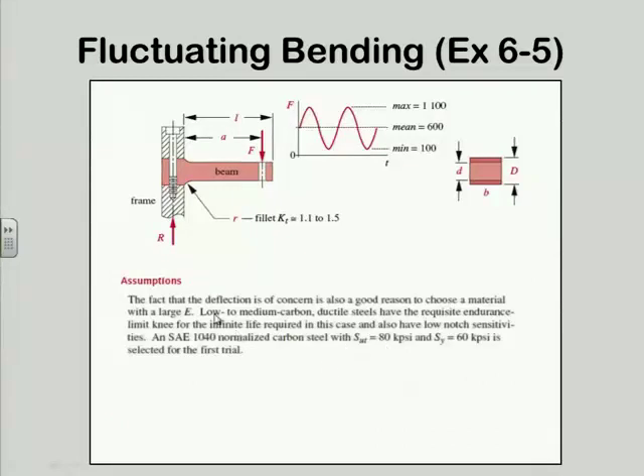I'm going to assume that I will use a medium carbon steel because it's nice and ductile. It's got an endurance limit, has a knee, and it's pretty low notch sensitivity, so that's a good choice for this particular case. If I don't need the hardness for wear, then I typically will not go up into the high hardness regime because I'm going to lose ductility. I'm going to pick up a lot of strength. I mean, the ultimate tensile strength goes way up, but I lose ductility and I pick up notch sensitivity. So I sort of chase my tail a little bit in the fatigue department by going to higher strength steels.